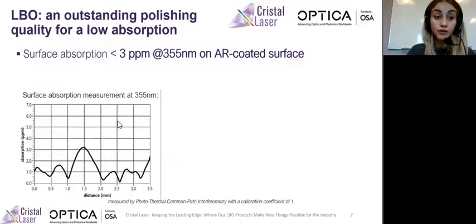Here we have a surface absorption for a coated crystal, which is under 3 ppm at 355 nanometers. The crystal is coated with an anti-reflective coating. A surface absorption that low is made possible by combining an extremely smooth optical surface with a very low residual absorption in the thin film layers.